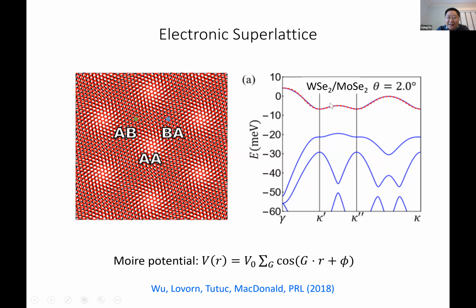But here, this is a calculation based on this continuum model, and you can see that instead of simple parabolic bands, this band breaks up into many mini bands, and these are the Moiré bands. For example, in this example, the lowest Moiré band is separated by a gap of more than 10 millielectron volts from the next band.